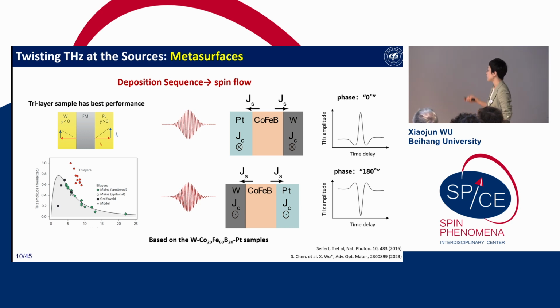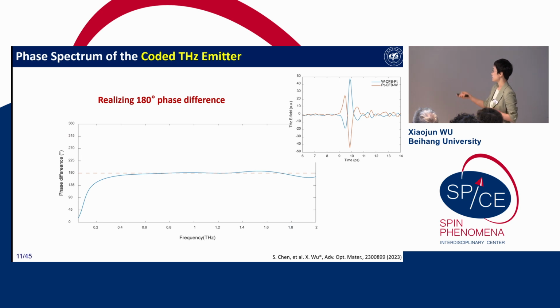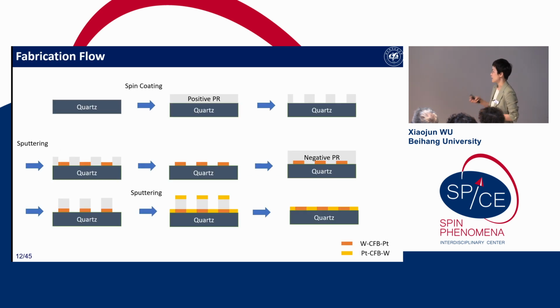What we have done, we can see here, is that if we only change the illumination facet, the radiated terahertz phase can directly give you 0 degree or 180 degree, and this can even be very broadband. So this gives us 0 and 1. That means 0 degree or 180 degree, so that we can fabricate a metasurface directly on this nanofilm.